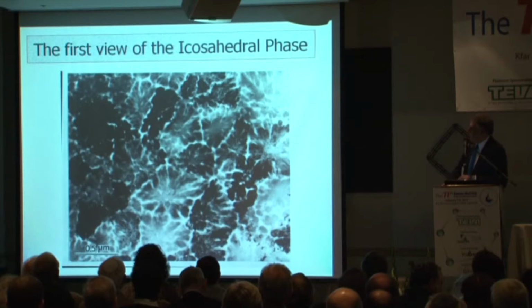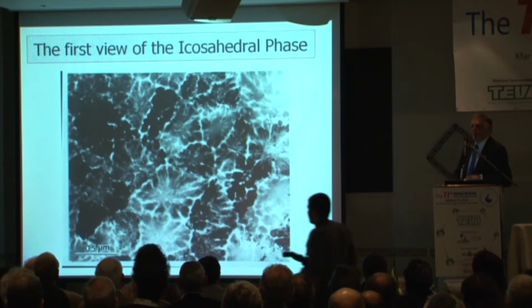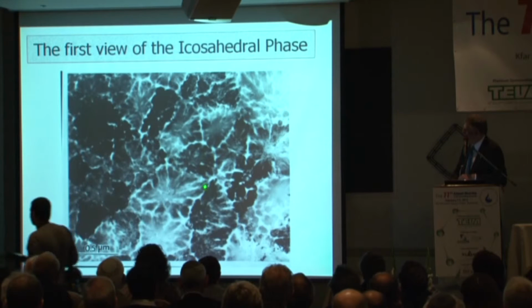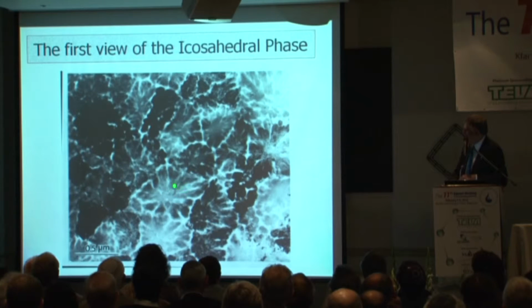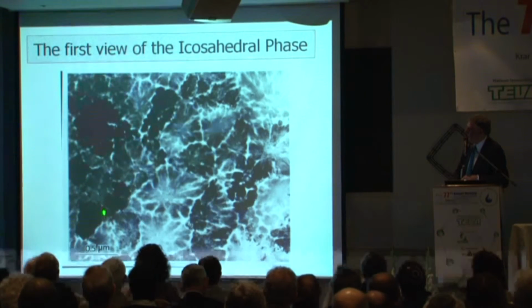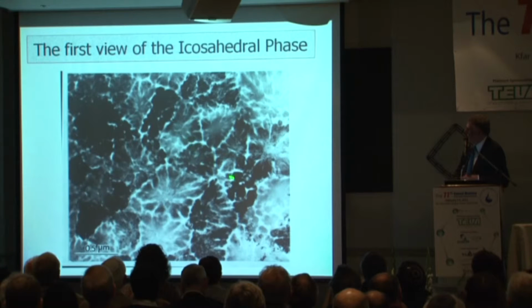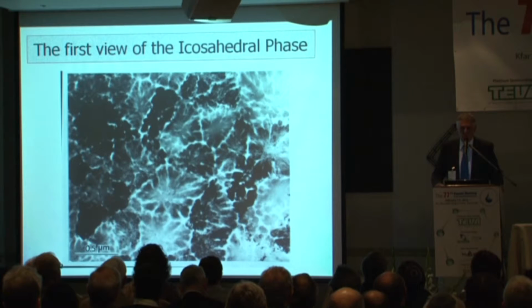And what you see here is that each one is a grain. Each one, like this, is a single crystal. Okay? And so this is a polycrystalline material. And the size of each one of these is of the order of a micron or two. And you notice that some of the grains are very black. I mean, pitch black, this and this and this. So this is what drew my attention. I've never seen such crystals before, so black.